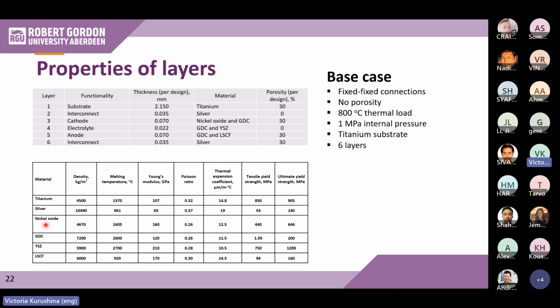From the material properties, you may know that there is a quite valuable difference between the thermal expansion of silver as a material and the coefficient of thermal expansion of the other materials used for this specific cell design, so that the maximum thermal expansion could be expected specifically in these interconnect layers.